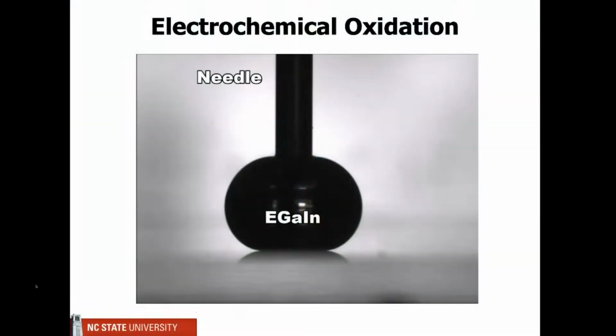So you can imagine how surprised we were when we did this. We took a droplet of the metal, and oh, by the way, this is in base, so there's actually no oxide on it when it starts the experiment. And we applied a voltage, and what we were expecting to see was nothing, just something form on the surface, but instead, it spread like a pancake.